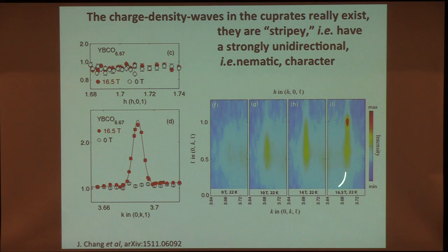The other thing is that this is a scan in the interplane direction. All of the charge density wave things that have been looked at previously, this short range stuff, corresponds to rods of scattering, which means that there's essentially no correlations in the third direction. This high field charge density wave is really order. It's a finite width, but it's a Braggish peak. It corresponds to correlation lengths of at least 50 angstroms in the interplane direction as well. So the correlation volume of this is orders of magnitude bigger than anything that's been seen previously. So we really know what's going on here. We're getting unidirectional charge density wave order when we suppress superconductivity.